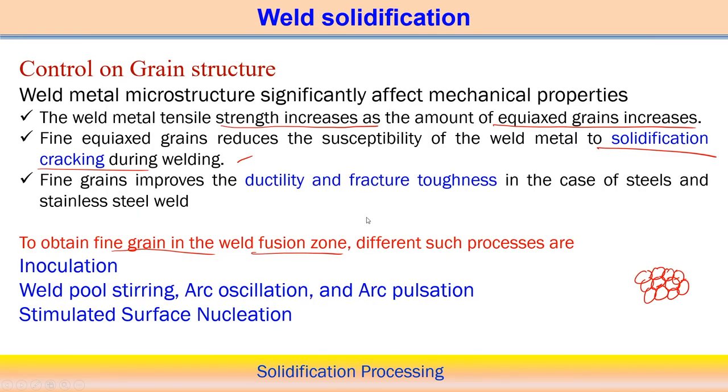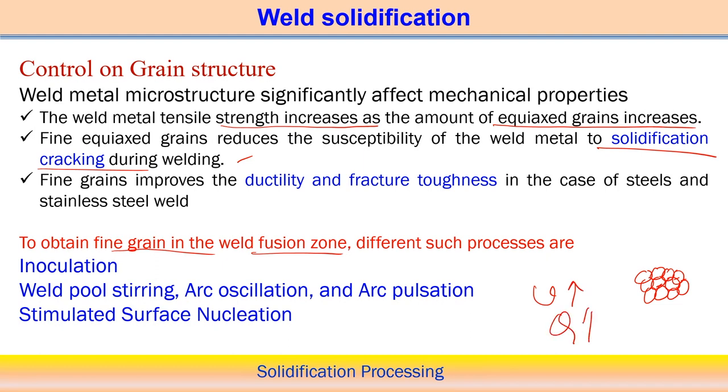Now, once we look into all the effects of grain solidification associated with the welding process, what the different aspects of solidification are, and what the influence of the process parameters on the solidification is, we can understand that in weld solidification, it definitely starts with the columnar structure at the boundary, and very close to the center, it will promote the equiaxed structure. This is the usual procedure. Of course, if we try to enhance the equiaxed structure, we can modulate the material properties and process parameters, for example, high welding speed and very low heat input. Both try to promote this kind of fine or equiaxed structure.